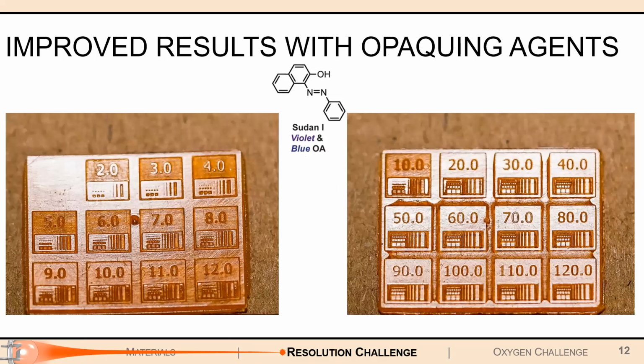We can see right here that once you dope that resin with the opaquing agent and print it out, it's a lot more defined, a lot more rectangular and a lot more detailed. It looks a lot closer to the actual print file, so we have some really nice resolution increases there. The downside, though, is that the 1 second square on the far left no longer appears. That's simply because the opaquing agents do absorb some light, and that slows down your polymerization. Therefore, one of my jobs in this project was to find that sweet spot that balanced accuracy of resolution with high polymerization speed.